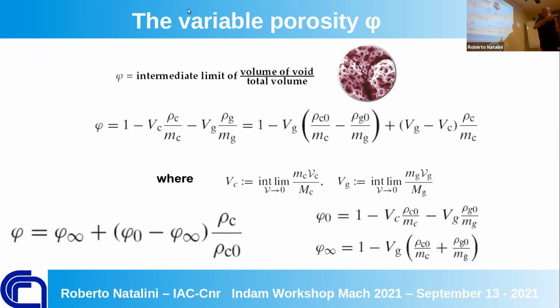Even the scale of this kind of models is completely different. And here you see that you take porosity. Porosity is a very confusing tool. Porosity does not exist because if you are, I don't know, an atom, you don't see porosity because you are inside of the atom, or there is nothing. So there's just 0 or 1. But on average, in the intermediate limit, when there is some stability, that's the volume of void divided by the total volume. So it's a macroscopic idea. Porosity does not exist, and it can change even in the same material. And here there is a sort of derivation, but the idea is that it's a linear quantity. I mean, the volumes are just the sum of volumes, so that's the derivation.